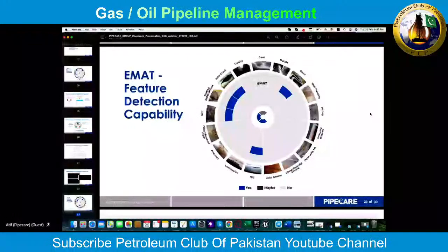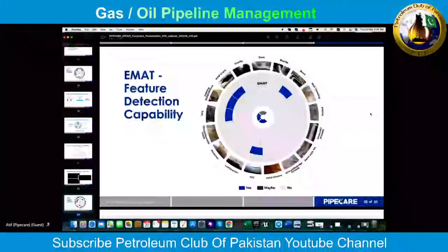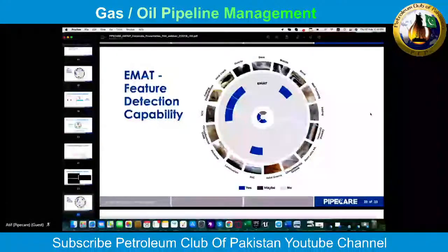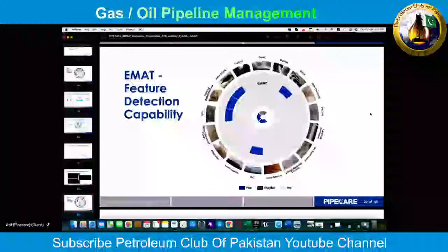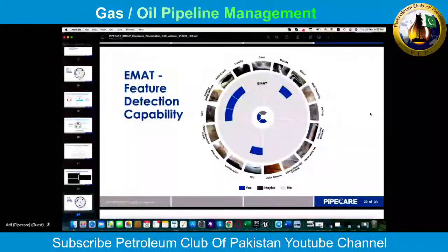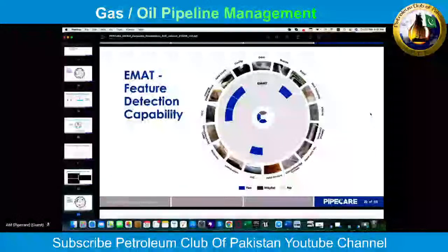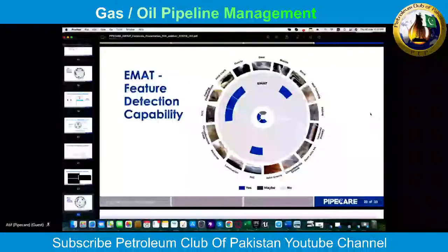Now we come to the EMATS tool, which is also a tool for crack detection, but a very special tool. The ultrasonic crack detection tool, as it uses ultrasound, needs a liquid couplant. And this causes a headache for all gas pipeline operators, because no gas pipeline operator wants to have a liquid in the pipeline, because this requires dewatering, drying, meaning additional expenditure. Of course, there is the option to run a batch with an ultrasonic crack detection tool, but still the pipeline needs to be cleaned up afterwards, needs to be dried before the normal operation can be restored.